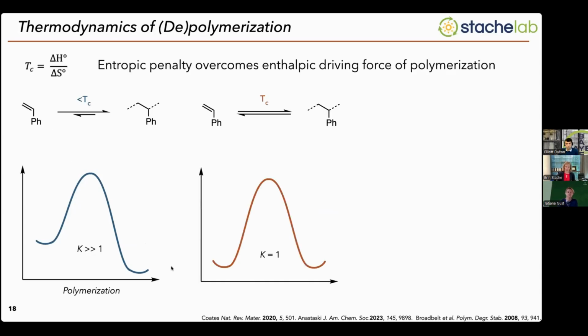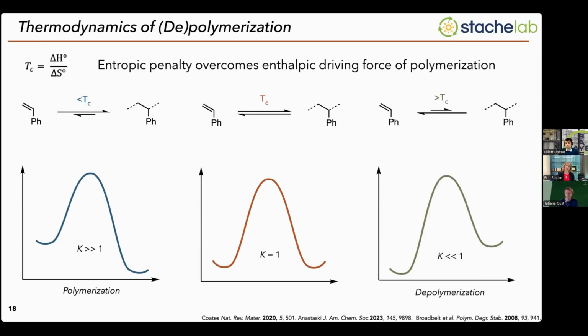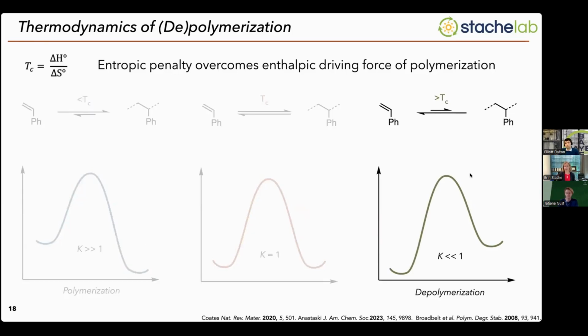But there is a temperature dependence for polymerization. And at a certain point, the entropy of stringing all these monomers together is going to overcome the enthalpic driving force of the polymerization. This is known as Tc, or the ceiling temperature, in which the rates of polymerization and depolymerization are equal. They essentially reach an equilibrium. If you go above the ceiling temperature, now you've actually destabilized the polymer enough that it wants to unzip back into the monomers. And so this is the regime where we really need to be if we want to induce depolymerization of commercial polymers or any polymers.